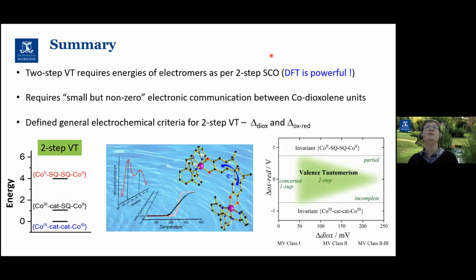So just to summarize a few things, the DFT is proving to be a really powerful tool and really a nice agreement with the experimental data. Two-step VT seems to require the relative energies of the different electromers basically along the lines of two-step spin crossover. So the mixed spin or mixed valence state has to be less than halfway in between the two extreme forms. In order to get a two-step VT transition, therefore, that requires small but non-zero electronic communication between the two halves of the dinuclear complex. And if you like electrochemistry, which not all of my students do, we've got a nice little correlation diagram that will apply for any of these bis-dioxolene complexes so we can sort of figure out where we are in terms of getting two-step VT if that's what we want to do.